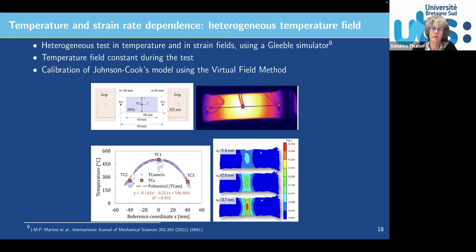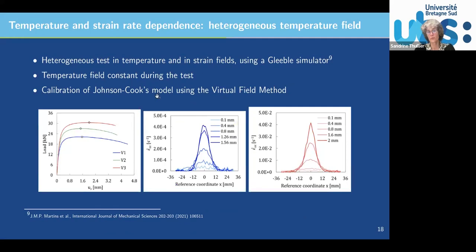And an infrared camera was also used in order to capture the full temperature field. So you have an idea of what is the temperature field over the x coordinate, which is the coordinate along this direction. So you've got both, in this case, a localization of the strain in the center, but also a temperature field, which is non-homogeneous. And the idea was also to calibrate a Johnson-Cook model, considering both, it's a multiplicative model. So you've got a hardening term multiplied by the strain rate dependency multiplied by the temperature dependency. So the idea was to try to identify all the components.